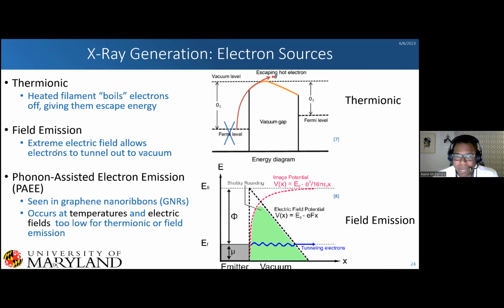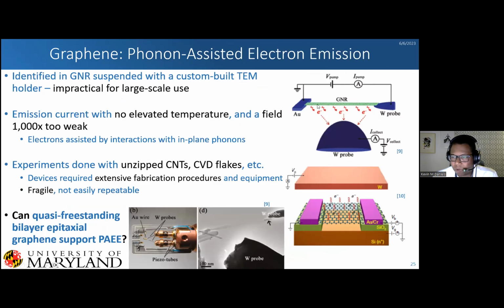Of course, there's field emission, where you have some very, very sharp point and you're applying a really high electric field to allow your electrons to tunnel out. So having something that doesn't require extreme fields or extreme heat, that was the idea. As I said before, electron emission from these graphene nanoribbons was demonstrated, showing that you can actually get emission without putting much effort in terms of temperature or field. The basic consensus was that you're getting emission currents with no elevated temperatures and fields far too weak to be able to get that kind of emission out.